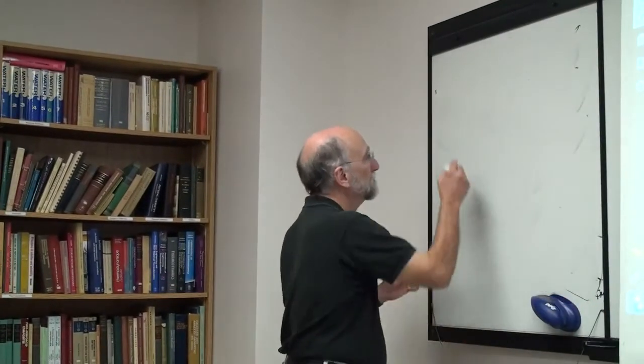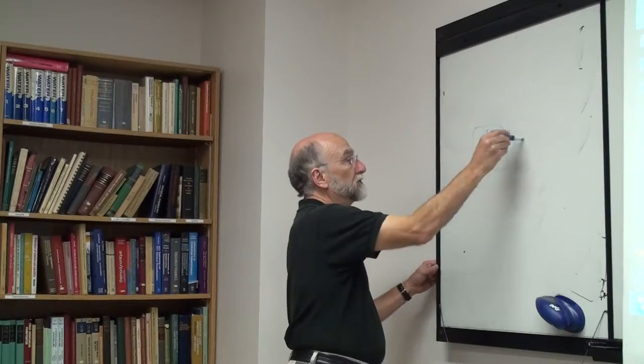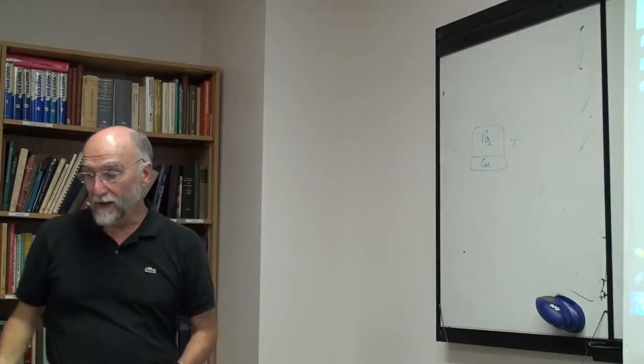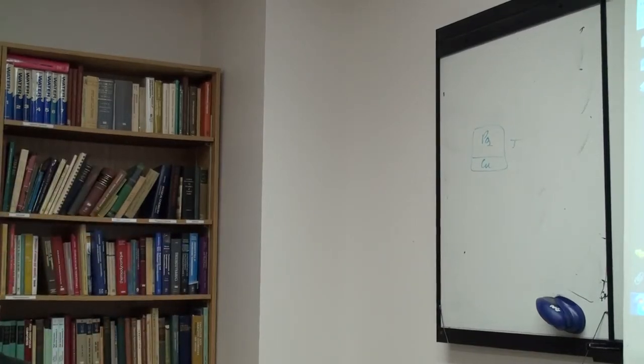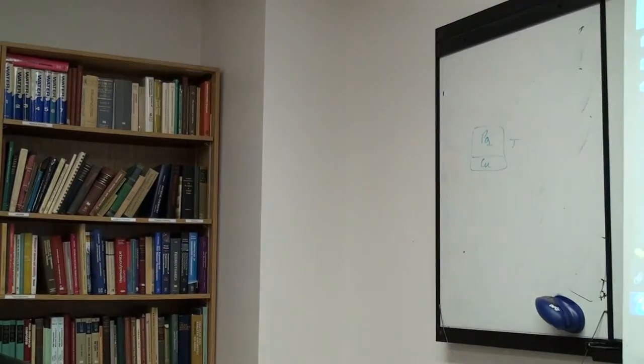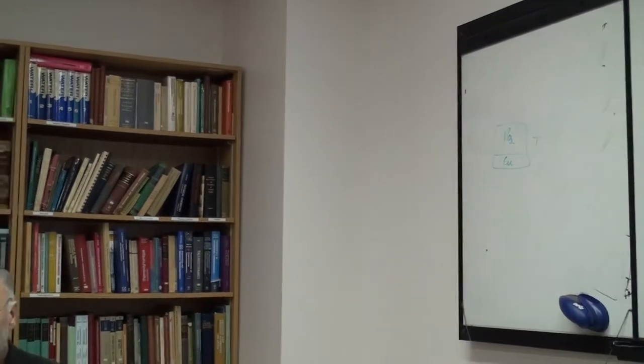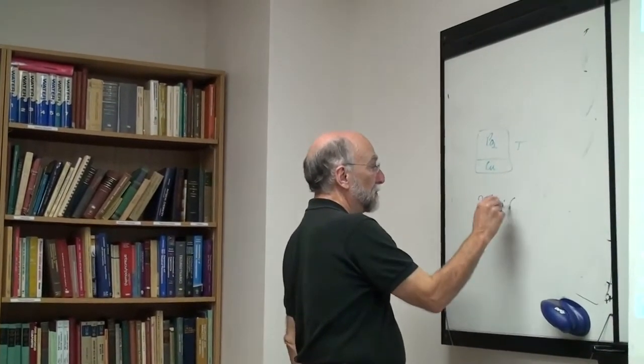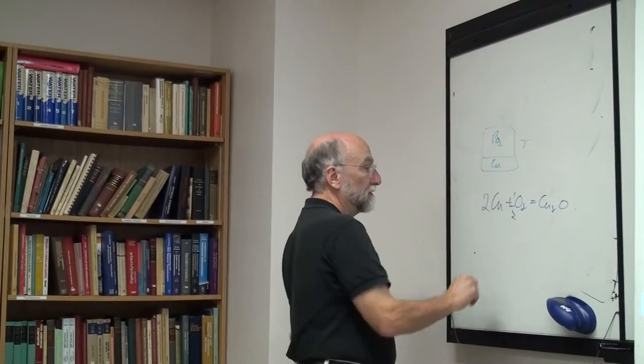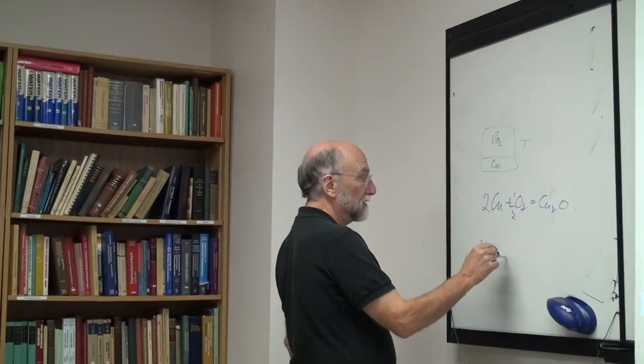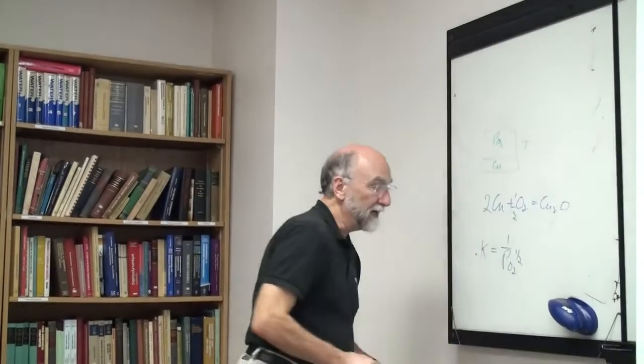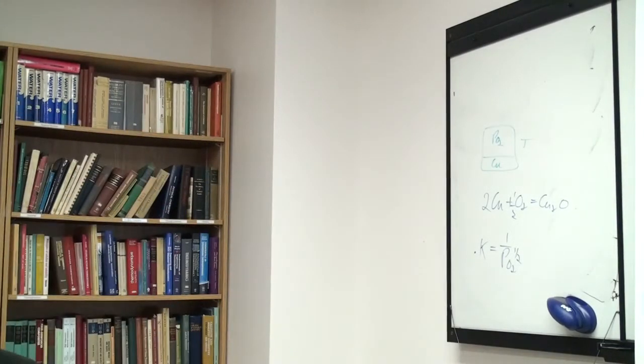So again, same idea, you have a box, you fix a PO2, you put some copper in the box, you fix a temperature, you let the thing reach equilibrium. What do you have at equilibrium? At this particular temperature, say 400 degrees, if your oxygen pressure is very low, you'll have copper. As you increase the oxygen pressure, you'll reach a point where the reaction's at equilibrium. 2 copper plus half oxygen gives you Cu2O, then there will be an equilibrium constant, which is 1 over PO2 to the 1/2, and when the pressure is such to satisfy that equilibrium constant, you'll have Cu2O. If you increase the oxygen pressure more, you'll reach a point where the two oxides are in equilibrium. If you go higher, you're in a one-phase region, and so on.